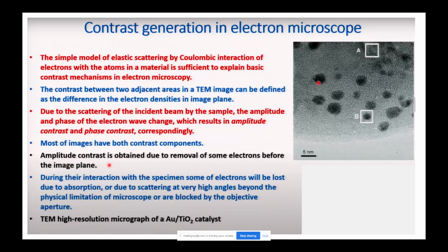Amplitude contrast is what is obtained due to removal of some electrons before the image plane. Suppose your electron beam is coming and has a certain amplitude. When it interacts, due to the removal of some electrons before the image plane, amplitude contrast will generate. During the interaction with the specimen, some electrons will be lost. It is coming, interacting, and some is lost. Why? Because of absorption, or scattering at very high angle beyond the physical limitations of the microscope, or they are blocked by the objective aperture. So that's why this amplitude contrast is generating.